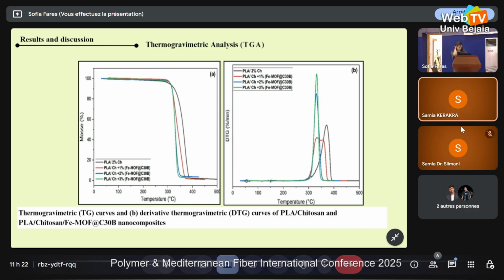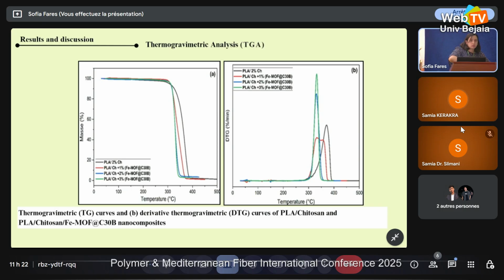TGA analysis. Here, as we can see in the DTG curves, these curves show wider degradation peaks, suggesting altered degradation behavior. And after the incorporation of the MOF into the PLA, the degradation accelerates. We can say that this incorporation accelerates the depolymerization of PLA, but still no significant structural impacts, making the composite suitable for food packaging.